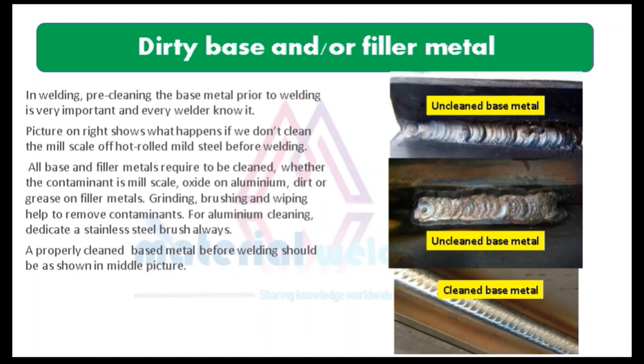Number 4 is dirty base metal or filler metal. Pre-cleaning the base metal prior to welding is very important and every welder knows it. The picture on the right shows what happens if we don't clean the mill scale off hot rolled mild steel before welding. All base and filler metals require cleaning, whether the contaminant is mill scale, oxide on aluminum, dirt, or grease on filler metals. Grinding, brushing, and wiping help to remove contaminants. For aluminum cleaning, always dedicate a stainless steel brush. A properly cleaned base metal before welding should appear as shown in the middle picture.